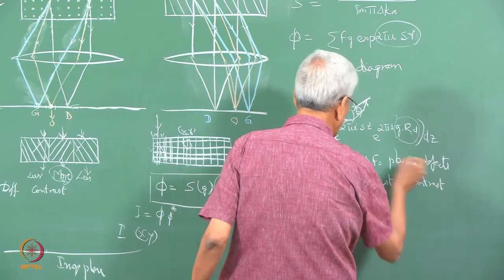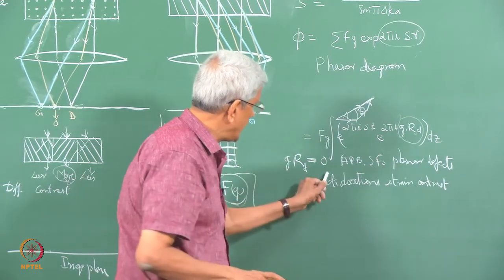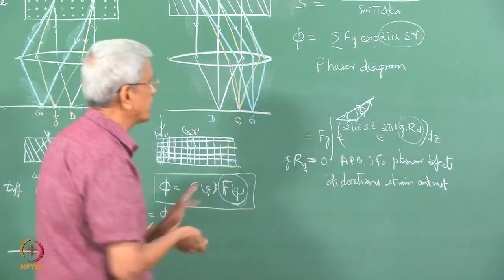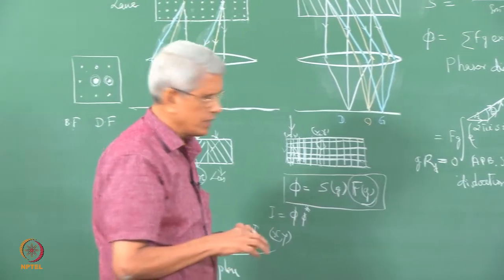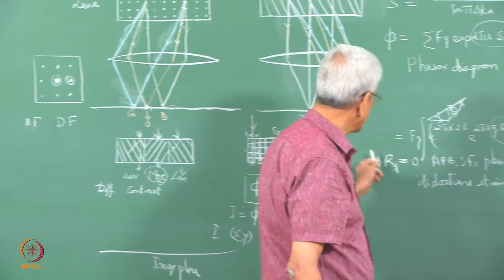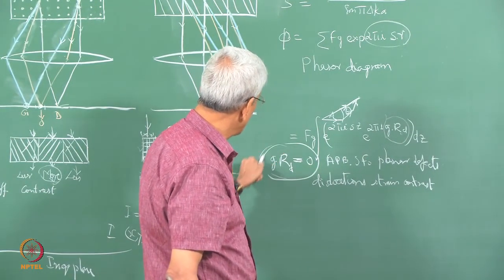In the case of planar boundaries, there is only going to be a relative shift of the planes, and in the case of dislocations, essentially displacement of atoms is going to take place around the line direction. So, we can find out the Burgers vector of the dislocation, the line direction, all this information could be obtained using this sort of analysis.